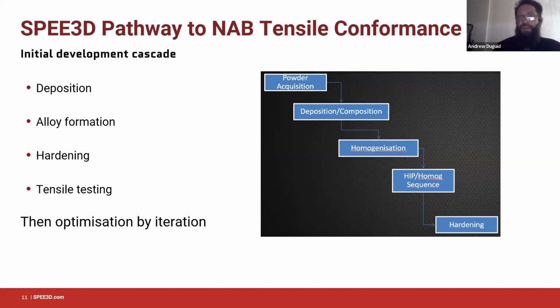And the next step, obviously, is to work out how to get that to deposit and then to hit the composition of the alloy that we're targeting. And that's a non-trivial step for reasons that we'll address in a moment. Having done that, we move into the heat treatment phase where we're looking at processes like homogenization and bond formation. And then the next step beyond that is hardening, because for any structural material, we have a strong preference for materials that have a thermal hardening mechanism. And the reason for that will become clear in a moment.